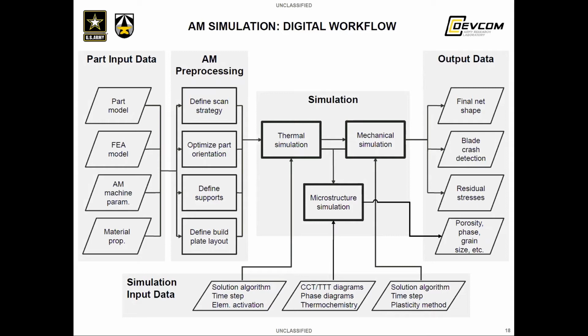The simulations themselves can be broken up into three interrelated categories, starting with thermal simulation. Here, the transient temperature is calculated throughout the solid part, the build plate as well, and even the inside of the simulated build chamber, all as a function of time. In an FEA simulation, for example, finite elements that are part of the part model are activated as the laser passes over them, and those elements then contribute to the thermal solution of the model.